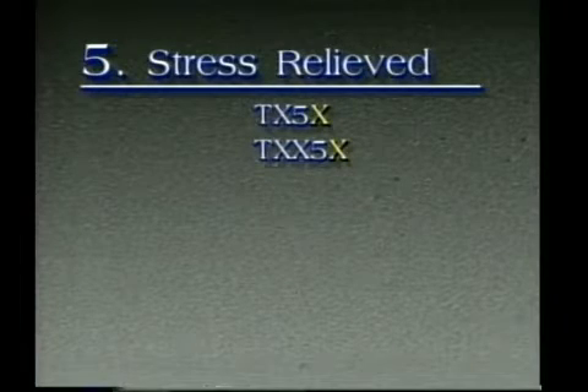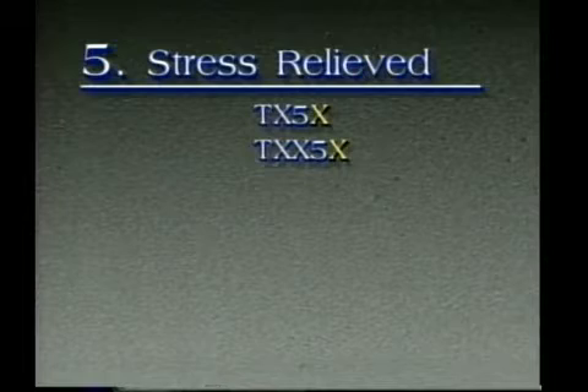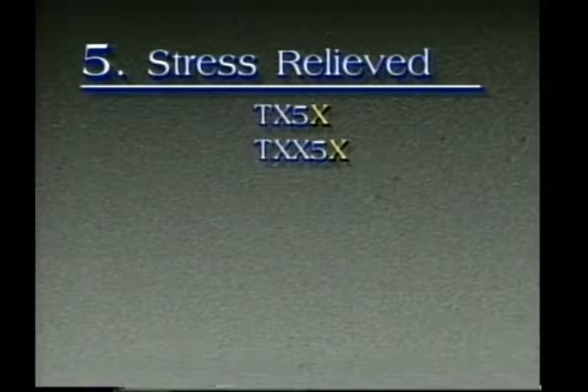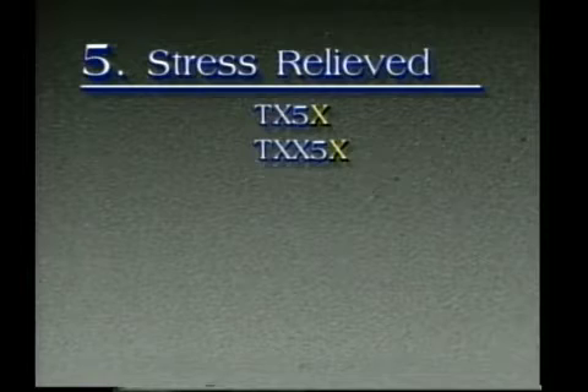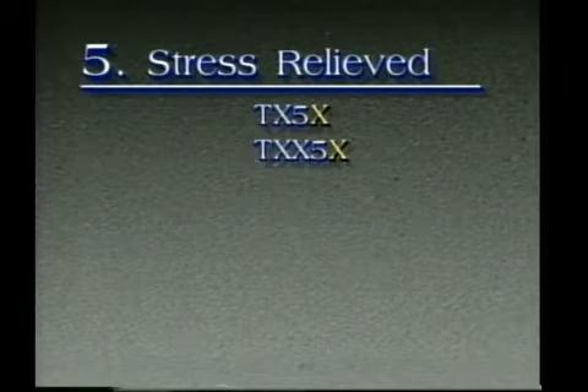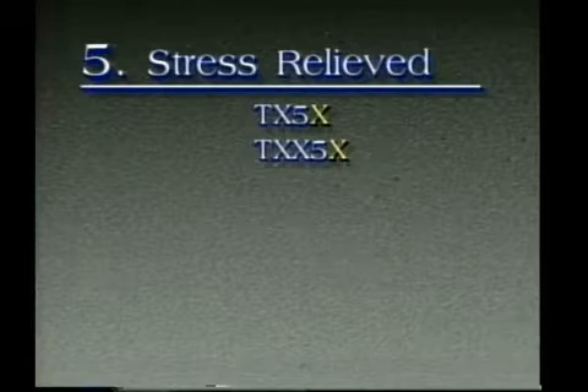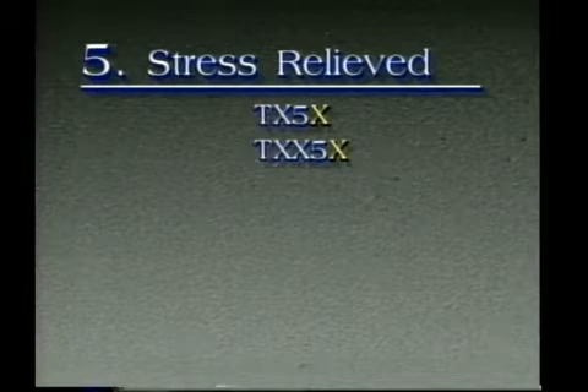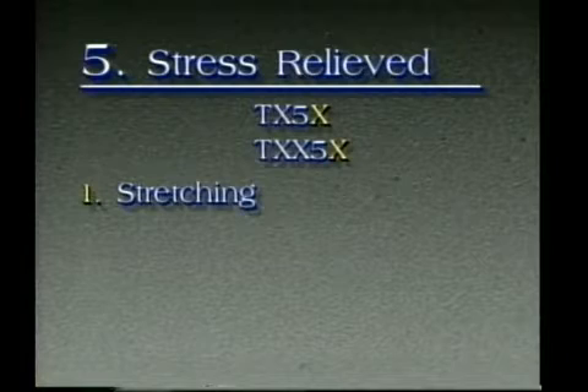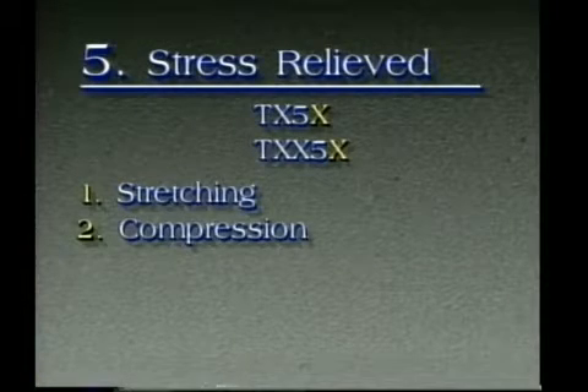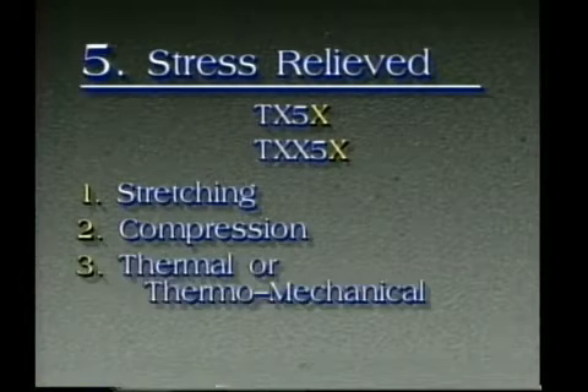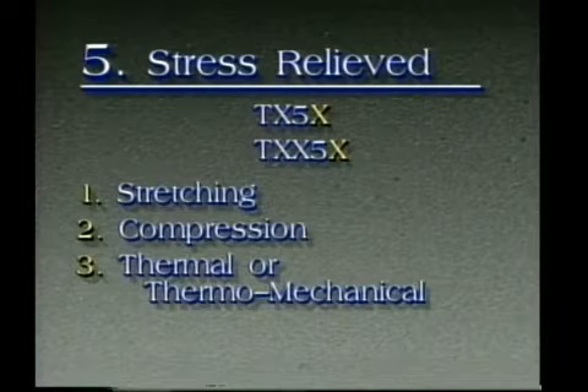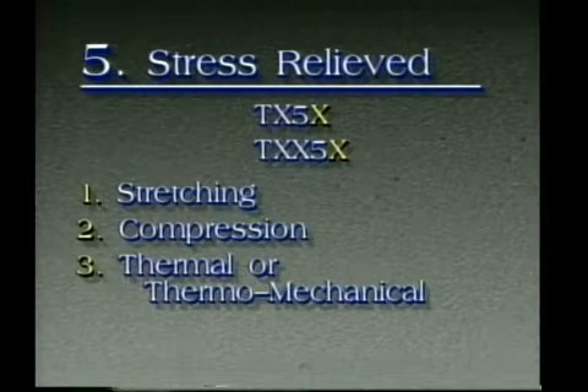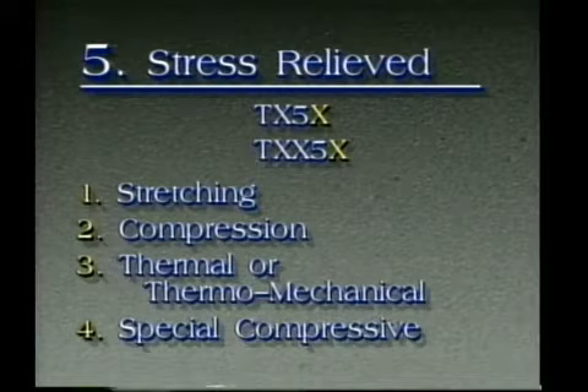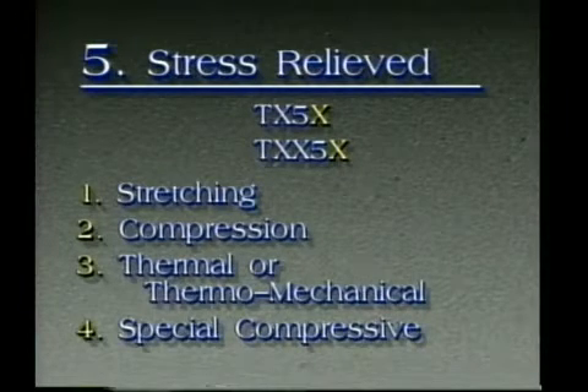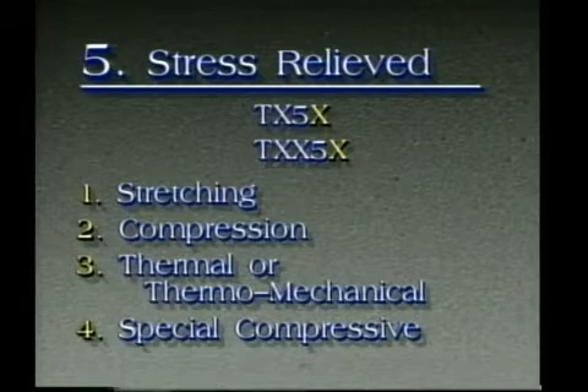A second descriptor is used to specify the type of stress relief used. So the nomenclature would take the form of TX5X or TXX5X. The secondary digits normally used in this case are the following: 1. Stress relief by stretching. 2. Stress relief by compression. 3. Stress relief by miscellaneous thermal or thermomechanical treatment. And 4. A special compressive treatment for die forgings where the finish forging die is used for the compressive treatment.